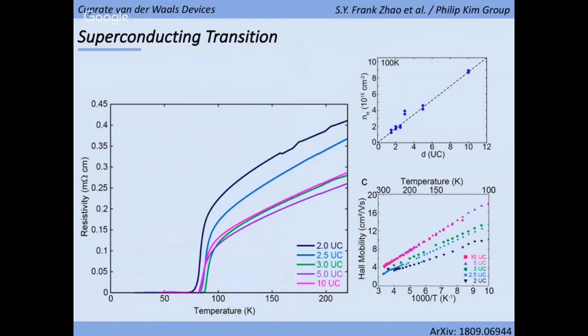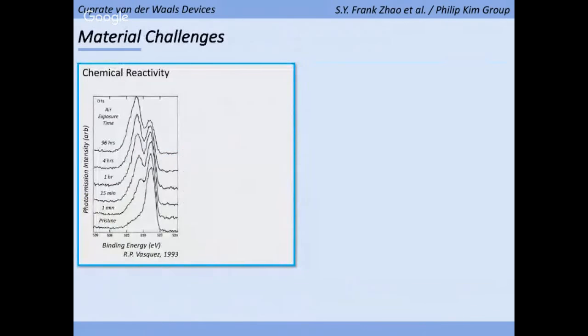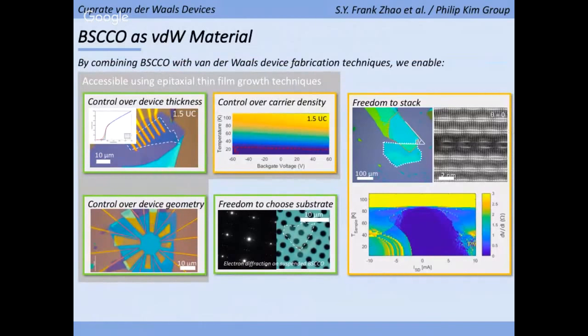The image you have, plane on top of plane. Yes. Right. They are the same plane. It's not folding. It's just that you pick up a stack. Okay. That's correct. So basically, we have designed a new transfer technique using polymers where we can directly stick the transfer polymer to our crystal, and then we can actually exfoliate it again using the stickiness of that polymer and put it down. A very strong polymer. And yes, it will pick up half of the crystal. The substrate is sitting outside.